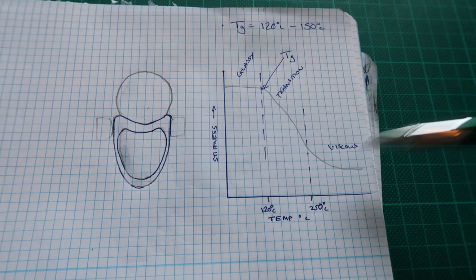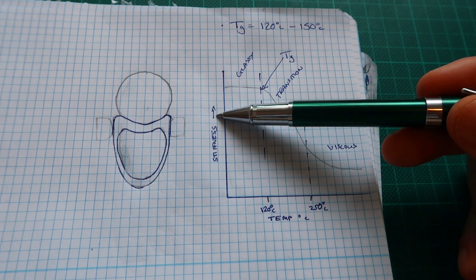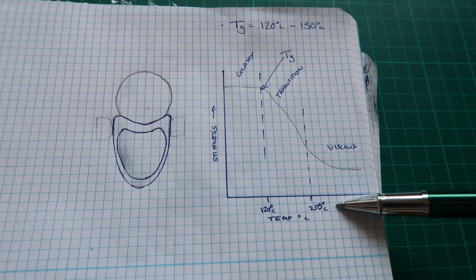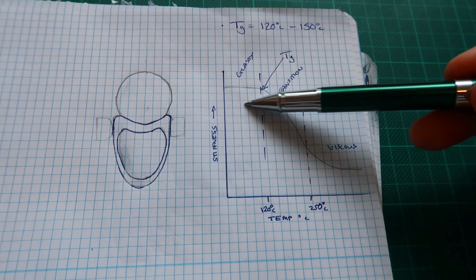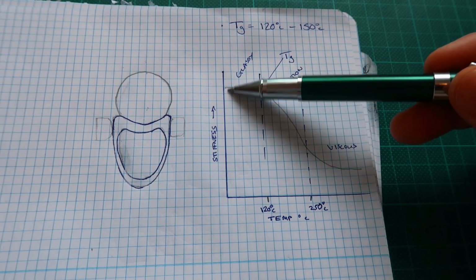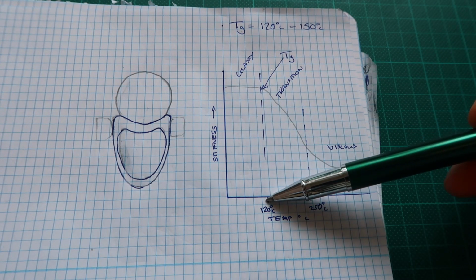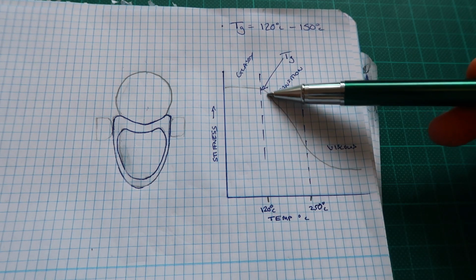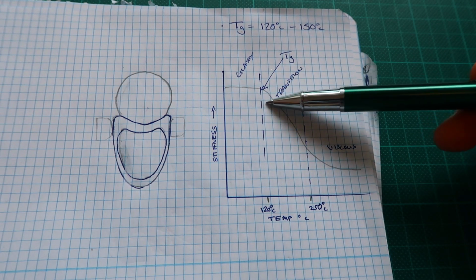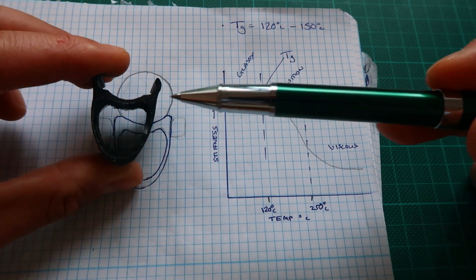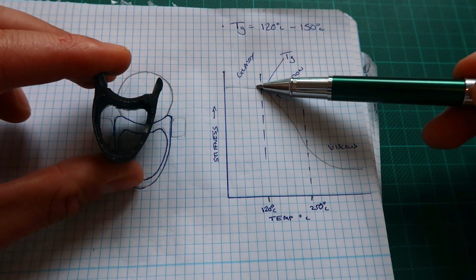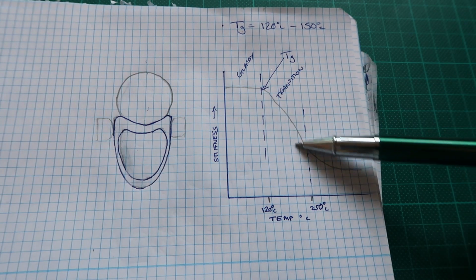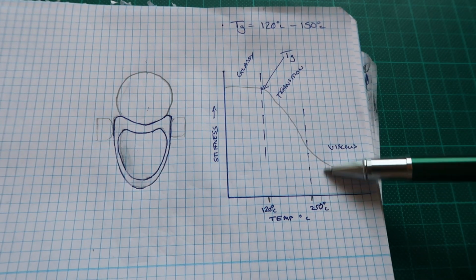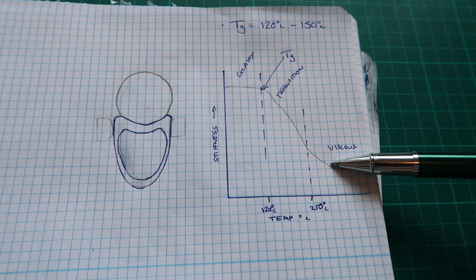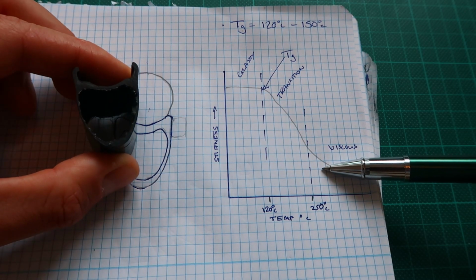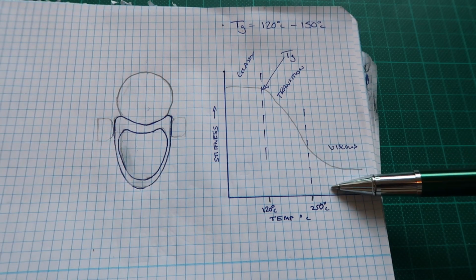Now, if you take a quick look on a graph, if the stiffness of the resin is on this axis and the temperature is on this axis, this is the area where you want to operate, and the resin is quite hard and glassy. After about 120 in a basic resin, it really starts to lose stiffness, and this is probably the temperature where this has got to, and it's failed. Now go really high, beyond 200 or 250, and you basically end up with a viscous liquid again. Even though the epoxy is a thermosetting polymer, if you get it really hot, it will go viscous.